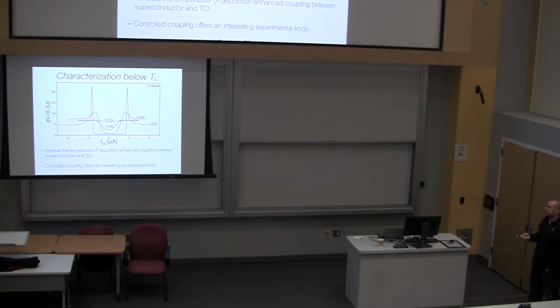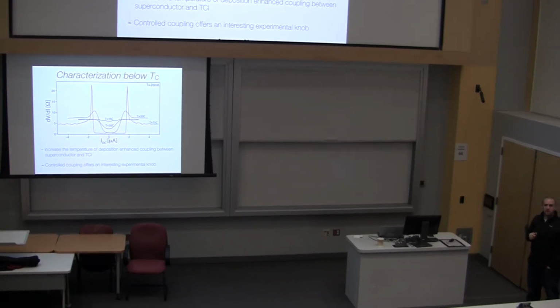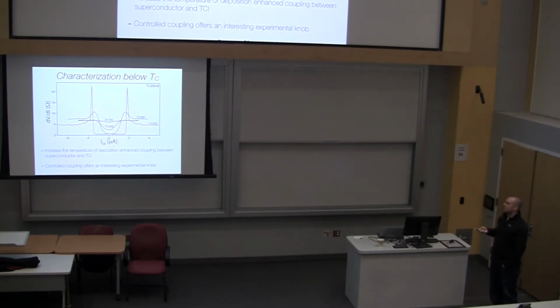And so you'll see a lot of curves that look like this. This is a plot of the differential voltage, the lock-in voltage, as a function of the DC current through the junction. If it is actually a Josephson junction, you would expect there to be no voltage developed as you start to apply a DC current. This is the voltageless superconducting state. And this only persists up to some value of current.